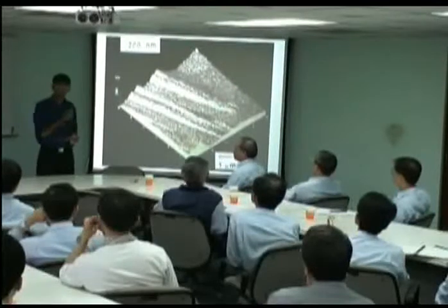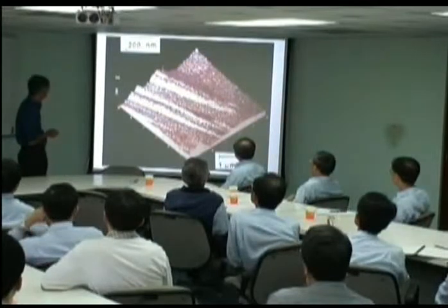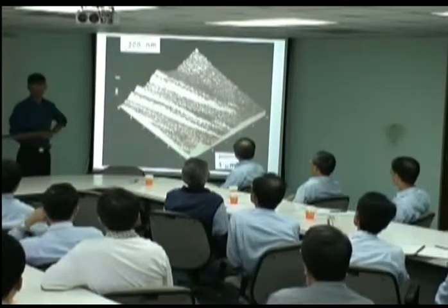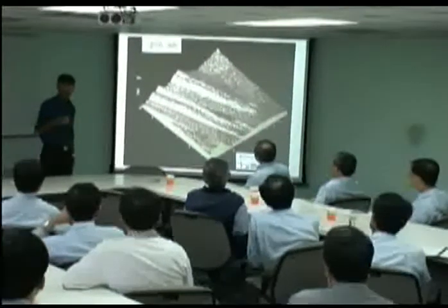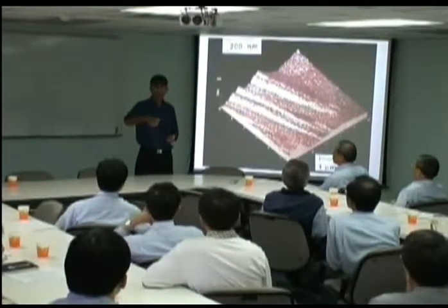There's one other thing I want you to notice very carefully from this: this is the plate of bainite. You can see that the adjacent austenite is also deformed. See this region here is deformed. The reason is that at the temperatures where bainite forms, austenite is quite weak. Its yield strength is low. If you're going to deform by a shear strain of 0.26, then you can't accommodate that elastically in the austenite. So you deform the adjacent austenite, and that has a very, very large effect.